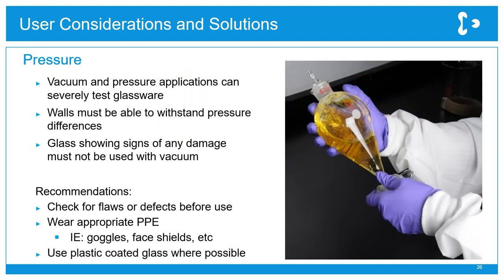And when you're working under pressure or vacuum, this is quite challenging for glassware. You do have to make sure you're using the correct glassware for this application, and it's important to inspect the glassware before each use as well. So when you're using glassware in a vacuum application, we should be using vacuum rated heavy wall glassware like Duran Pressure Plus, for example.